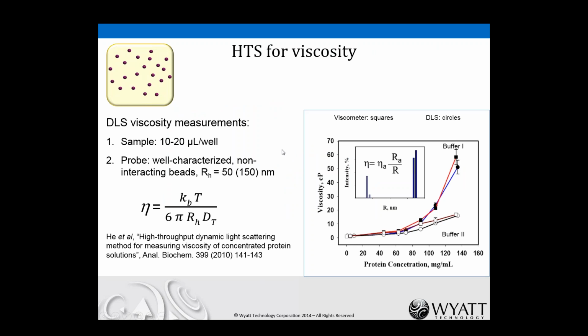Finally, dynamic light scattering can be used to assess viscosity. And in order to do that, what we're going to do is take, for instance, our highly concentrated protein solutions, put them into the wells, and spike into those wells some polystyrene beads of a known diameter or known radius. And we're going to invert the Stokes-Einstein equation. So normally, we measure the diffusion coefficient, we know the temperature, we know the viscosity, and we extract the radius or the size of the particulates. In this case, we know the size of the particulates, and we utilize this to extract the viscosity.